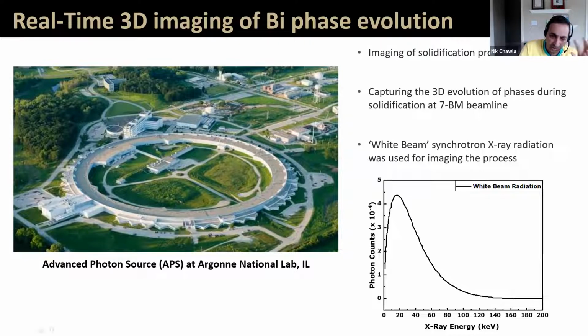So we can actually do tomography. And some of the data we have not processed as yet, but we also were able to collect energy dispersive spectroscopy kind of data at the beamline at the same time. Okay, and one of the nice things about this particular beamline is that it has what's called a white beam. I told you that typically the X-rays at the synchrotron are monochromatic, but in some beamlines we want to take advantage of much larger flux. And this is much more important when we get to higher density materials. So because we're dealing with tin and bismuth, we need much higher flux of photons, and so we use this white beam.